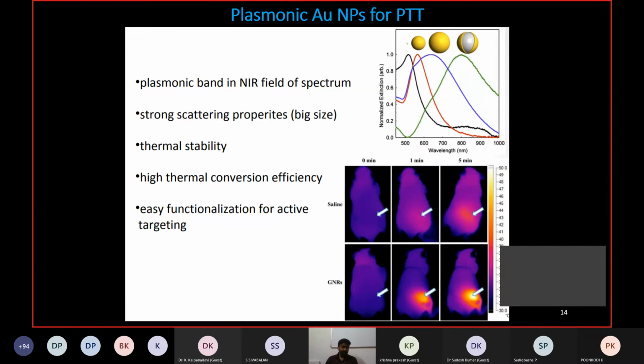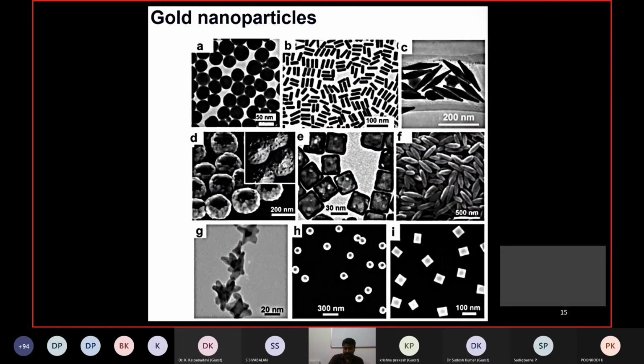This gold nanoparticle has plasmons. You should know what a plasmon is first. See, the shape is different. I'll come to the definition for plasmonic band and the plasmonic heating. Gold nanoparticles being metallic structures, they have a loosely bound electron on their surface, and that again varies due to the size. You know, most of the atoms are present on the surface. When it goes to the nano regime, the shape also does some trick.